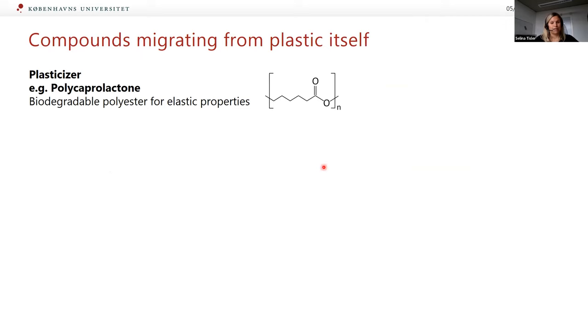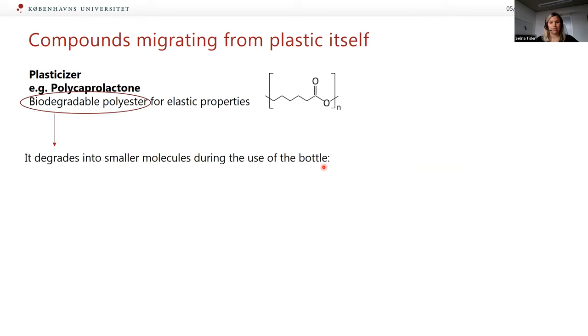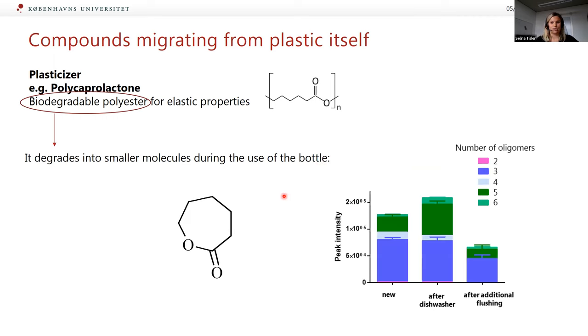Now to compounds we detected which are migrating from the plastic itself, we found polycaprolactone, a biodegradable polyester, which makes sense that they are in this bottle. But because they are biodegradable, we found smaller molecules from them, which were migrating into the water. They are these oligomers with different ring sizes from 2 to 6. And we see that they are in the new bottles, but after the dishwasher process, there's even more of these biodegradable plasticizers leaching out. And also after additional flushing, we still have quite some peak intensity left of these compounds.